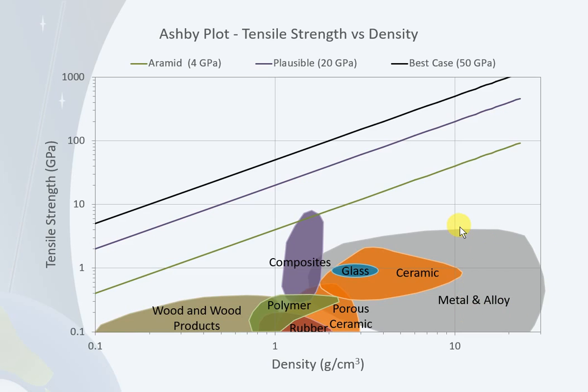While their tensile strength is higher, getting up to the 2 or 3 gigapascal range, their density is just too high, and so our strength per density ratio is insufficient. Metal just isn't going to get the job done. Ceramic and glass won't do the job. Rubber won't. Most polymers are out, with the exception of the aforementioned aramids, which make up that line.